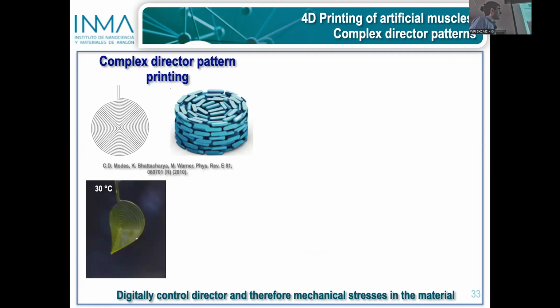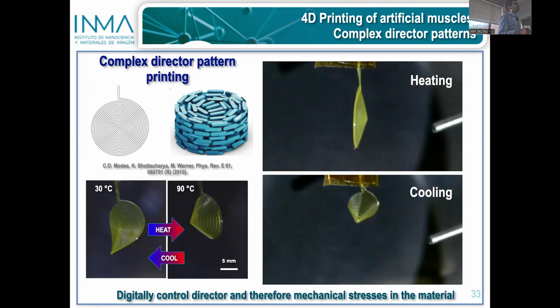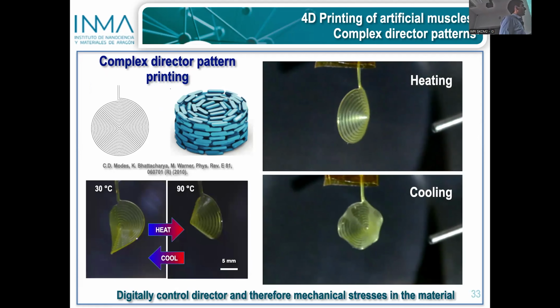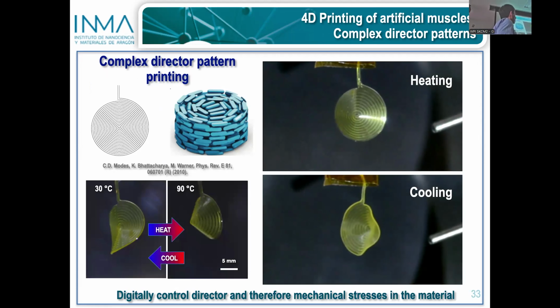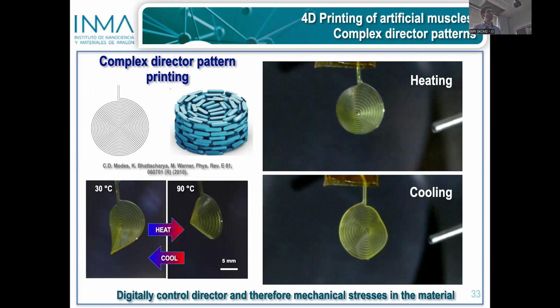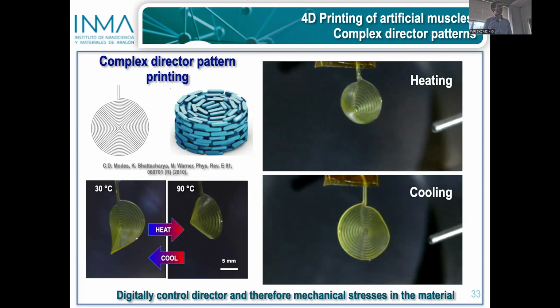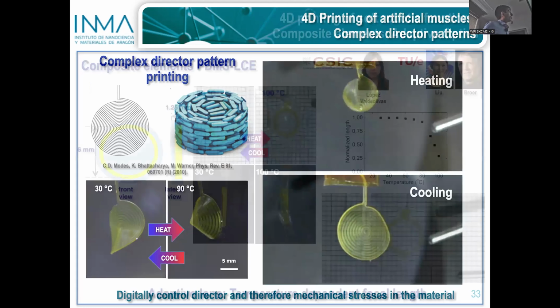Here you have again something. It's a spiral pattern that is a good approximation of the azimuthal pattern that we saw before. And here you see the sample at 30 degrees, but when you heat it up, as we explained before, the system goes into a cone. Now it is more clear, more neat, and when cooling, the system recovers the original flat state. So we are able to control these stresses in a quite precise way.